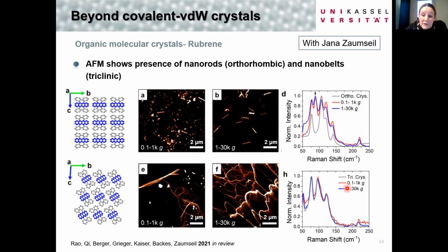The triclinic one is exactly the same. For the orthorhombic one, we see additional peaks. And this additional peak is known to be a surface disorder at the surface. Well, clearly when we do exfoliation, we expect that. And this here should also be active in the crystal, and this depends on the crystal orientation. And in our rods, this is random, and in a single crystal, it's fixed. So that's why we only see it in the exfoliated material.